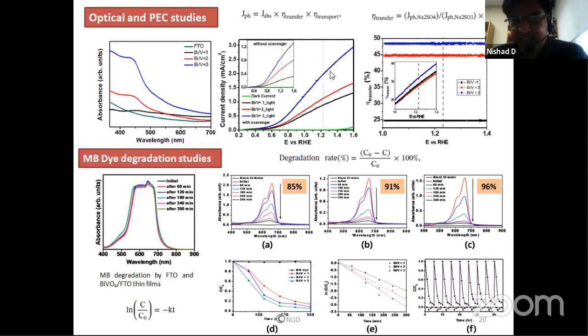And what makes this structure interesting is we tried to understand the eta transfer. Now this eta transfer is the transfer of charges from the semiconductor towards the electrolyte. So this is the efficiency with which the charges are getting transferred. You can see that the concentration ratio 3 of bismuth vanadate has a very high eta transfer of nearly 48% compared to the other concentrations. And we also tried to understand the eta transport, which is within the semiconductor, the electron hole pair generation. So you can see at this point also it has a very high transport efficiency. So that means this facet structure is very useful in increasing the current values, and thereby it can be utilized in separating the oxygen from hydrogen in the PEC cell.